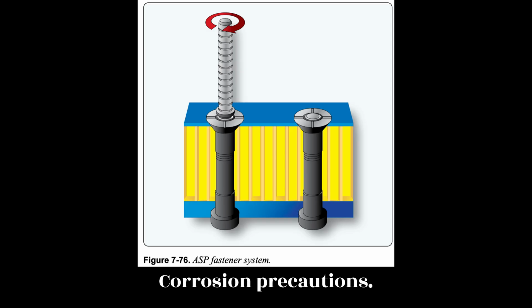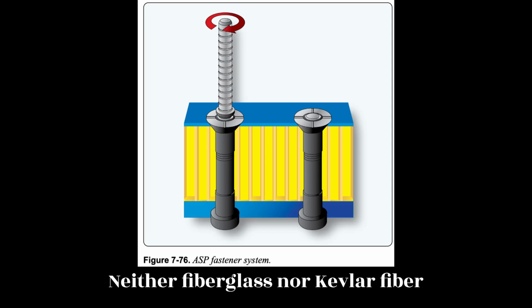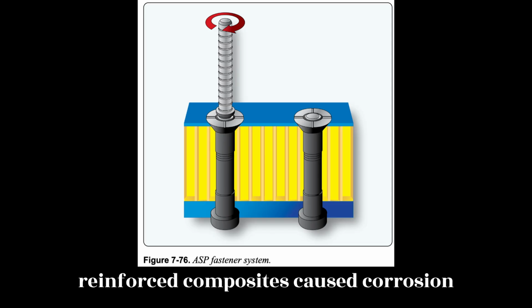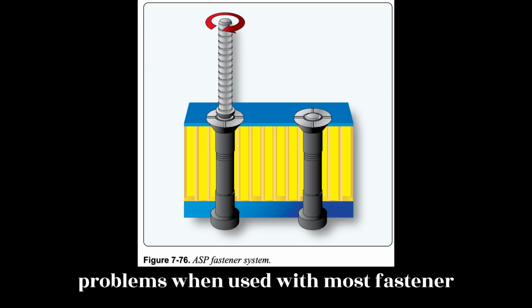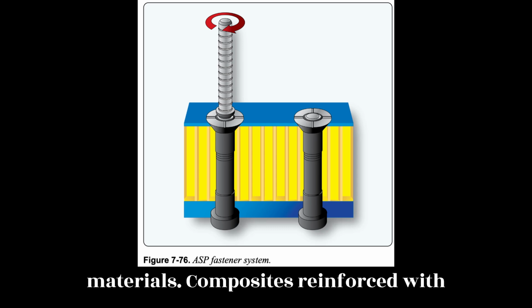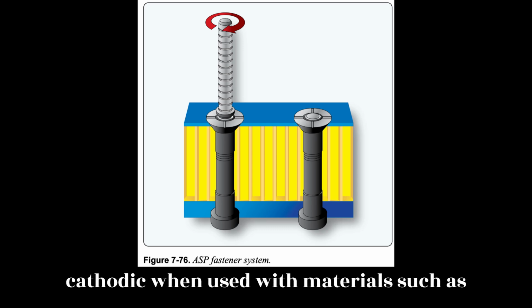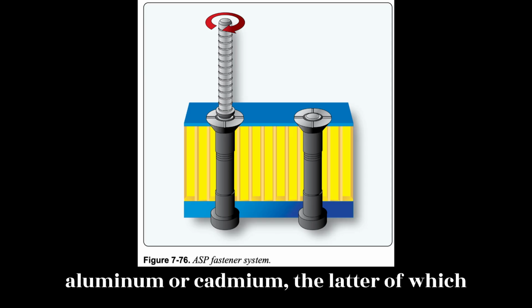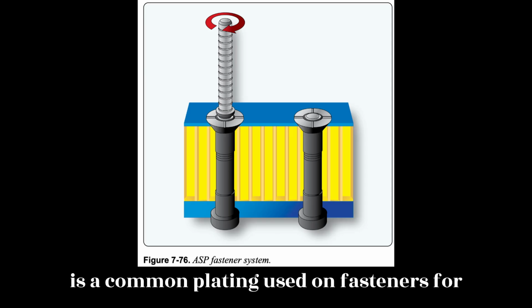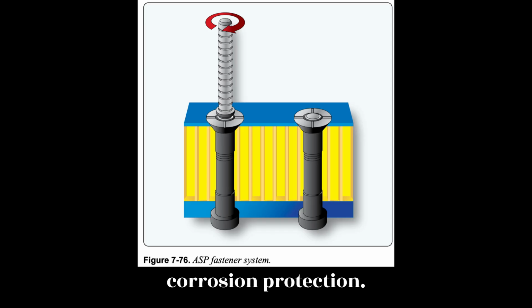Corrosion precautions. Neither fiberglass nor Kevlar fiber reinforced composites cause corrosion problems when used with most fastener materials. Composites reinforced with carbon fibers, however, are quite cathodic when used with materials such as aluminum or cadmium, the latter of which is a common plating used on fasteners for corrosion protection.